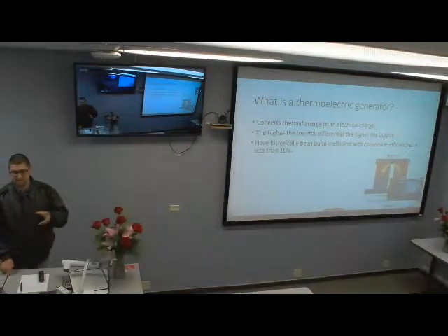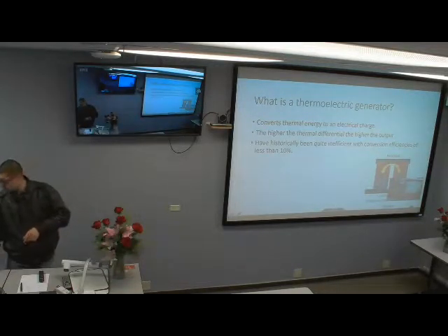Although historically they've had quite low efficiencies, ZTs of 1 or 2. The highest I was able to find any research on was a ZT of about 3.15. So with ZTs around 2, that's about a 10% conversion efficiency.